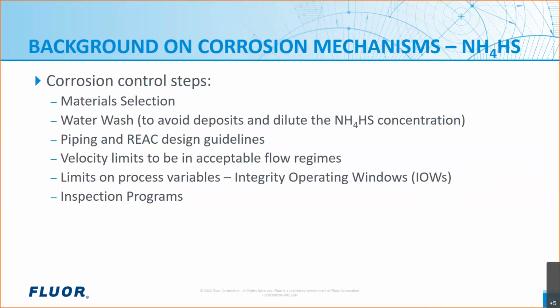Especially the inlet piping is often required to be what we call balanced, so that each flow split is just splitting into a T, not trying to do a header with a bunch of different branches coming off. Because you can see if you do that, you're going to have differences in flow inhomogeneity and differences in velocities. So piping has a lot of design guidelines. The REAC itself has design guidelines, like we usually require just either one row in the inlet pass or max 2 rows, because if you start having more rows in your inlet pass, again, the water distribution in the REAC is mainly going to only the bottom row of tubes in that inlet pass. So if you had more rows, the top rows could be starved of water.